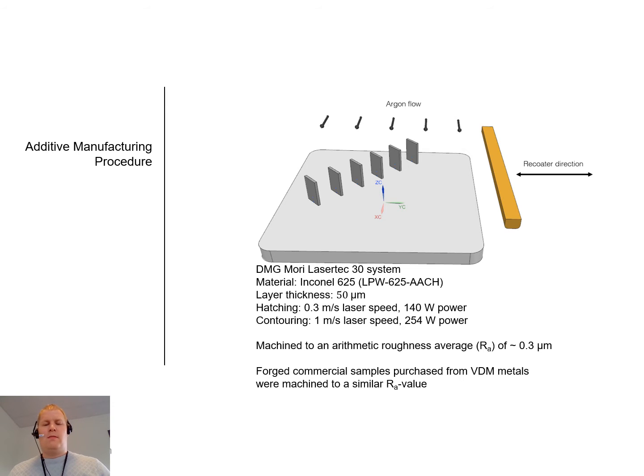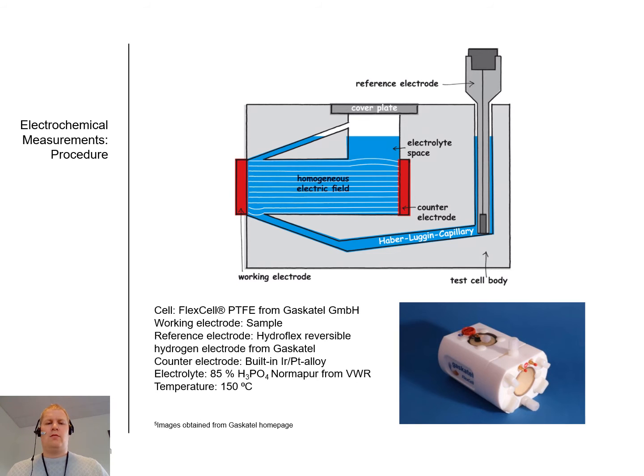After production, the samples were machined to an arithmetic roughness average of 0.3 micrometer. Forged commercial samples were purchased from VDM Metals and they were machined to a similar Ra value. The corrosion electrochemical measurements were conducted in a flex cell made of PTFE that we purchased from Gaskatel. In this cell you have the so-called three electrode setup, where the sample is known as the working electrode.